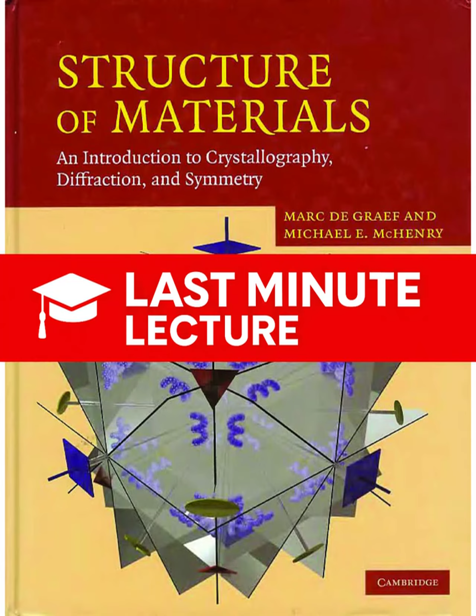And crucially, they all belong to the 0, 0, 1 zone, so their projections must lie on the great circle defined by the equator. And finally, the 111 family, the body diagonals. 8 of them. And because of the high symmetry, the angle between the 0, 0, 1 direction at the center and any 111 direction is a fixed specific value, 54.74 degrees. So those points are plotted inside the equatorial circle at that calculated angle.